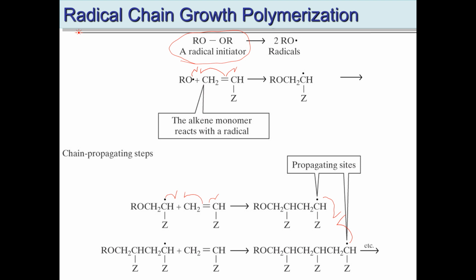So if you put in a lot of initiator, then you start out with a lot of free radicals really early on, the monomer concentration drops quickly, and you get a lot of chain terminations. If you want to grow a long chain, you use just a little bit of initiator, so that chain can grow a long time before it ever finds another free radical. So just tuning the amount of initiator that you put in and making sure oxygen is out of there and that it's a dry situation, then you can grow longer and longer polymers.